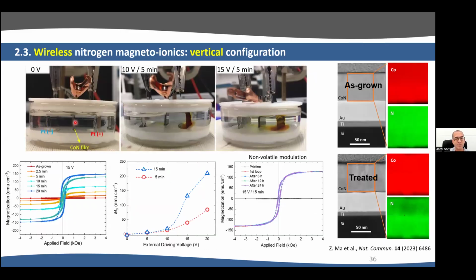Now here you can see photographs of the experiment. We apply this voltage. You can see again the side reaction, this yellow color. And now the film all becomes shiny, metallic-like. And we can modulate the magnetization, both with time and voltage. You can see here for different voltages and different times that we can control the magnetization in an analog way. And interestingly, if you stop the voltage, the magnetization remains even after 24 hours. So the effect now is non-volatile. So horizontal configuration, volatile; vertical configuration, permanent effect. Why is it non-volatile?